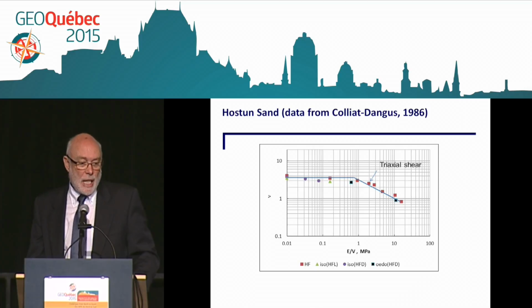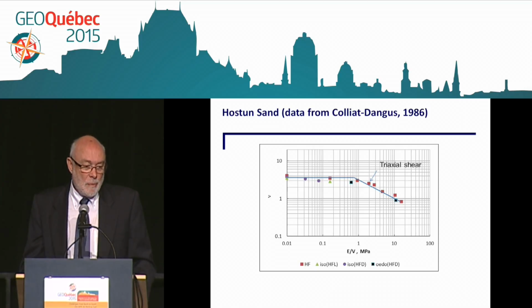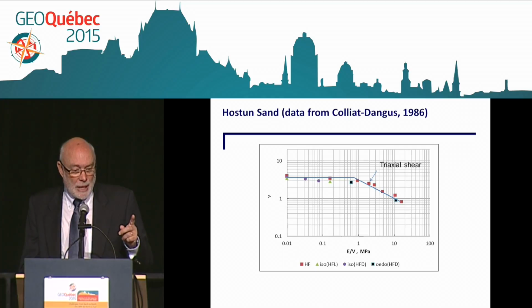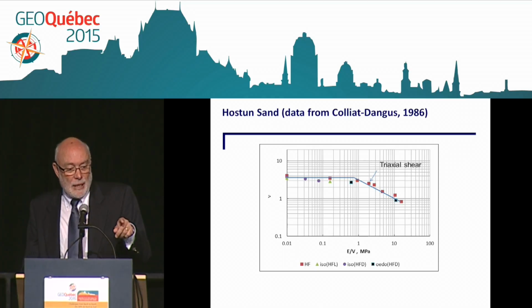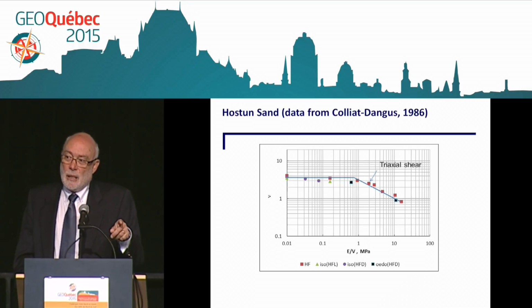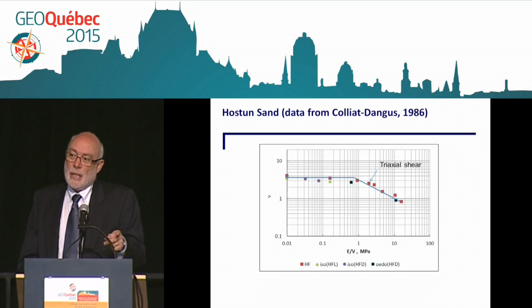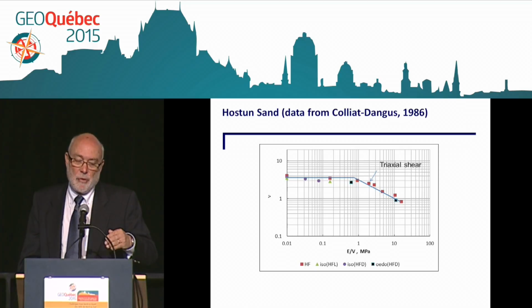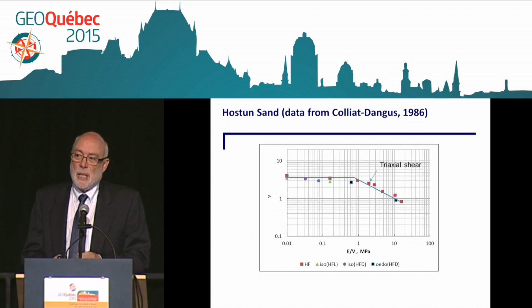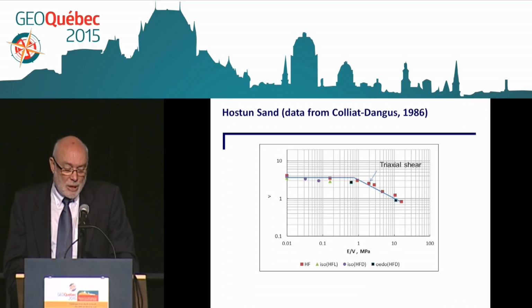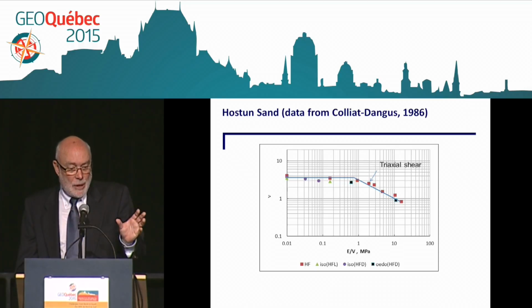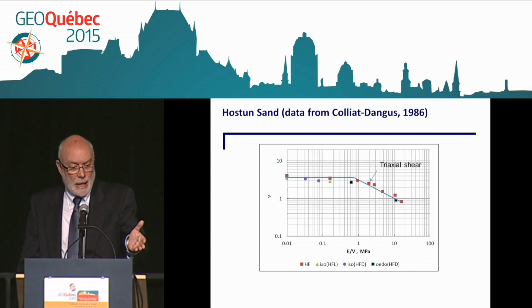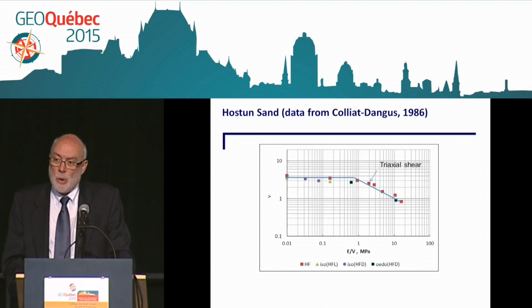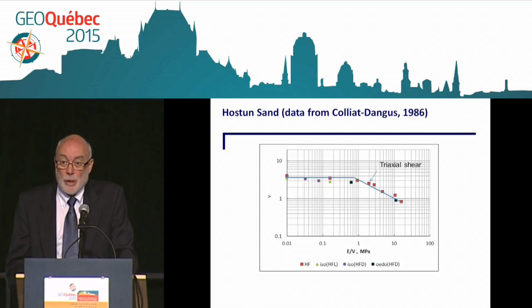And also French data on Hostun sand by Colliat-Dangus shows similar results. But now interestingly, we see that there is a critical input energy. When we reach that critical energy, crushing is starting or is proceeding. But before that, grains are not really fragmented, and it's really more a rearrangement type of process. So this is very important. Also, it shows that no matter what kind of test we do, we have a unique relationship for the material that we study.